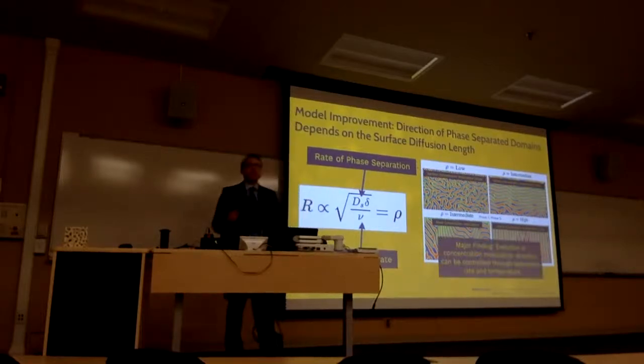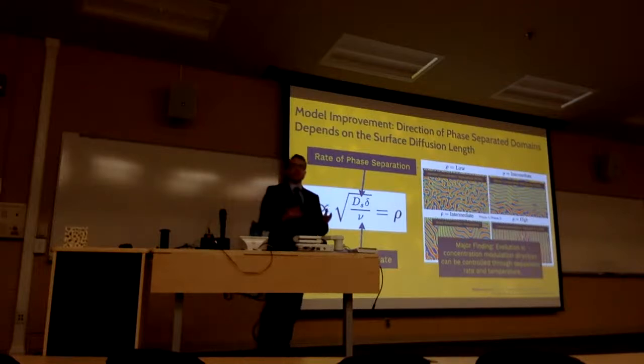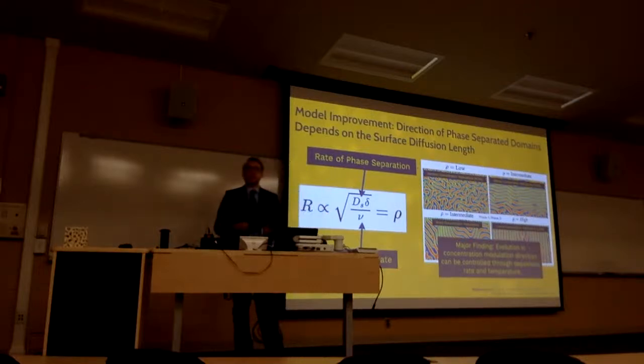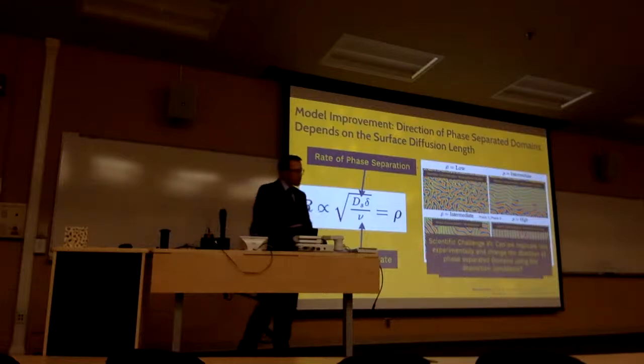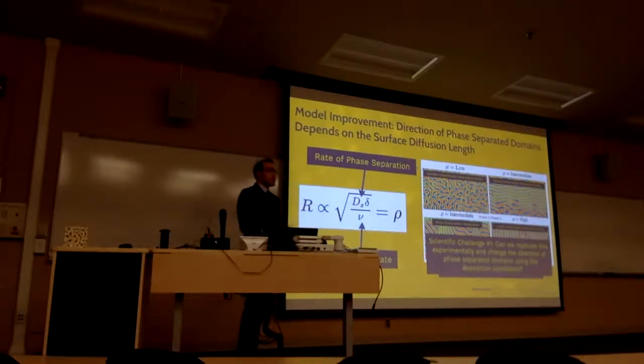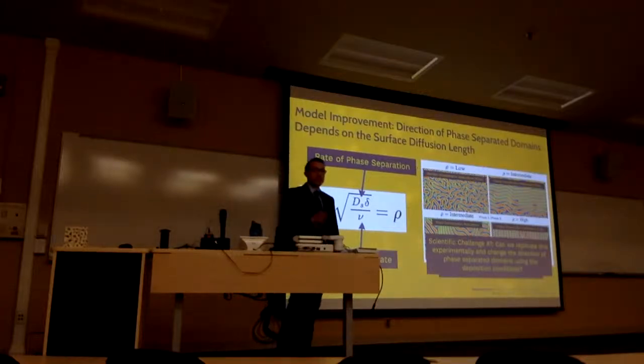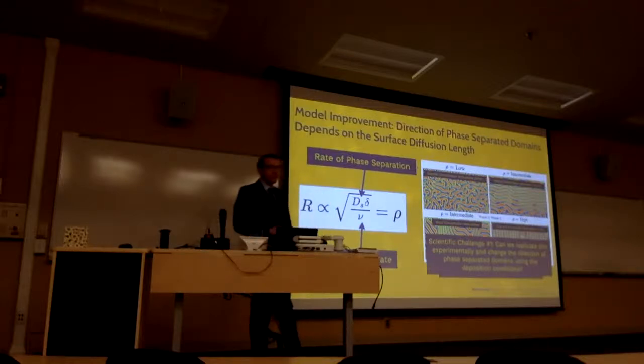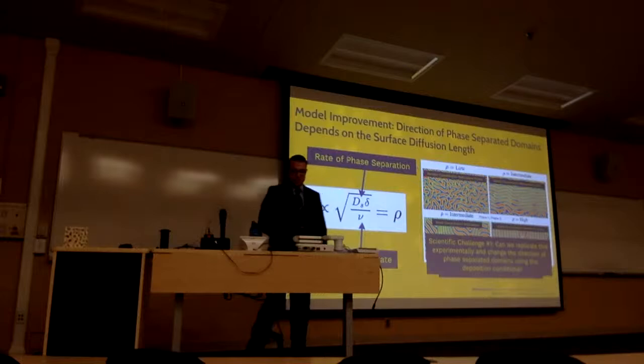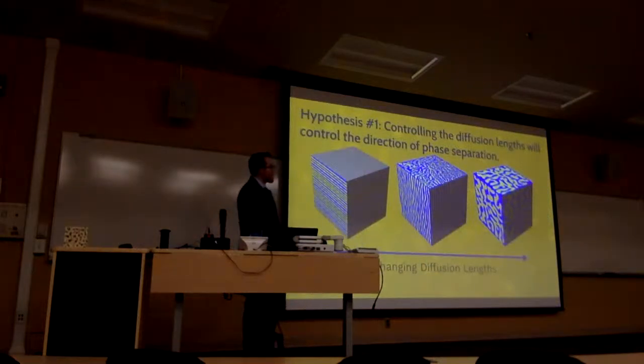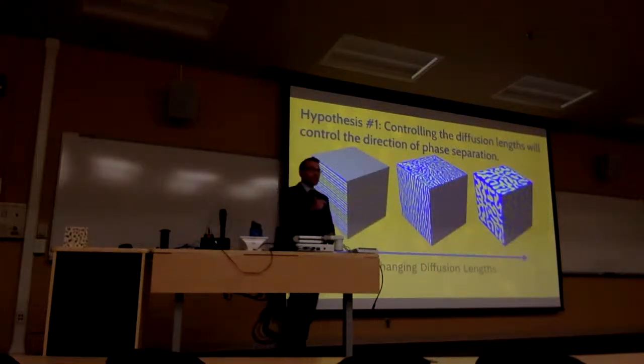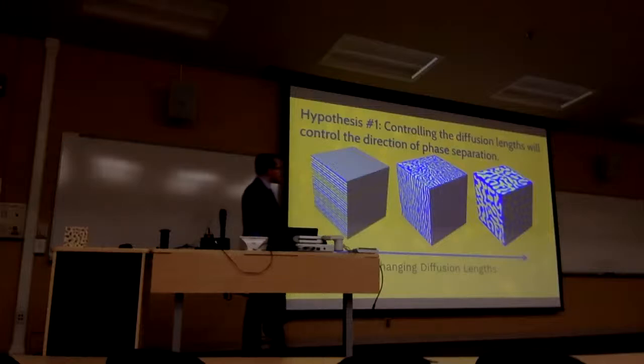So this was the major finding of this work, that you could change the direction of phase separation depending on the deposition conditions. So we saw this as a scientific challenge. Could we take this understanding and replicate it experimentally during PVD deposition? Could we heat the substrate and give it the deposition conditions needed to change the surface diffusion length to change the direction of phase separation? So our hypothesis here is that if we can control that diffusion length, we can control the direction of phase separation in these thin film morphologies.